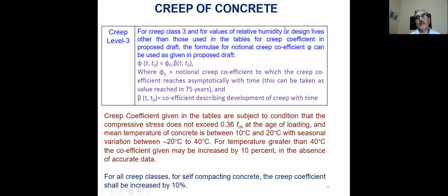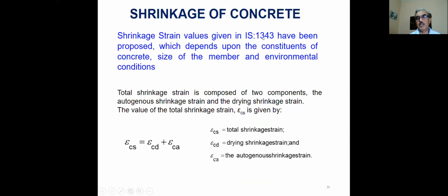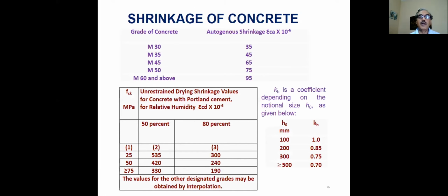Shrinkage of concrete is generally in line with IS 1343, merged with 456, and the same has been adopted. It depends upon the constituents to some extent, and is a combination of autogenous shrinkage and drying shrinkage. Autogenous shrinkage has been given grade-wise, and drying shrinkage has been given for two values of relative humidity in ambient conditions, 50% and 80%, for different grades of concrete. A coefficient to be multiplied is based on the size of the member.